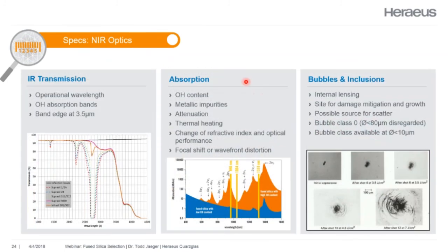So what are some of the specs that we should look at? Well, the infrared transmission, absorption, and the bubbles and inclusions are three of the important areas to consider. When you're looking at the infrared transmission, you want to consider what wavelength you are operating at. If we look at the transmission spectra of several of our different materials, we can see that some really have a lot of absorption in this band here.